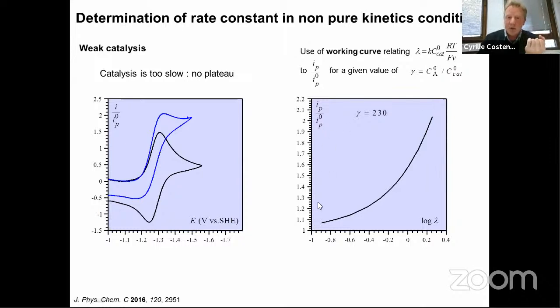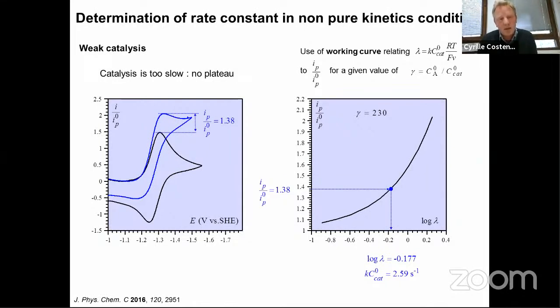So by simulation, you can predict the current of the catalytic CV as a function of this parameter for a given excess factor. And then you measure experimentally the increase of the current in the presence of the substrate. And from the position of this experimental data point on the working curve, you can get the dimensionless parameter. Okay, knowing the scan rate, you can measure the rate constant. So this is how you have to treat the experimental data to extract kinetic information and to get the rate constant for a given catalyst in given conditions.